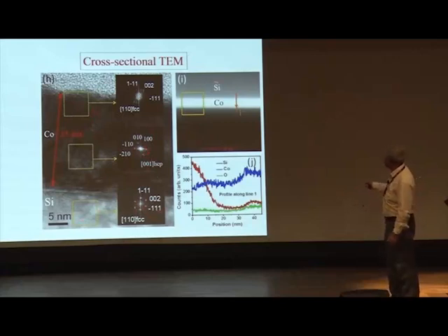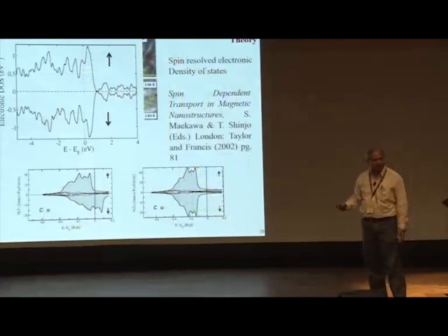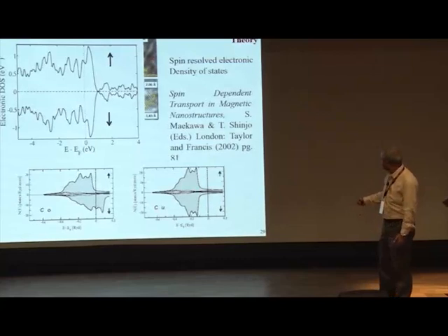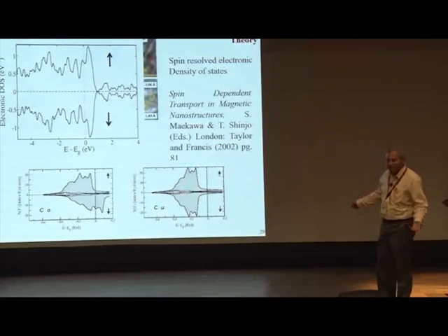Now if you take the fluorescence yield going across this cobalt layer, this is what you see. The cobalt actually has slightly higher intensity near the surface. That also corresponds to high cobalt. If you take FCC cobalt, FCC copper, then they are symmetric, and we know that copper has no magnetism. So this situation has become similar to this situation.